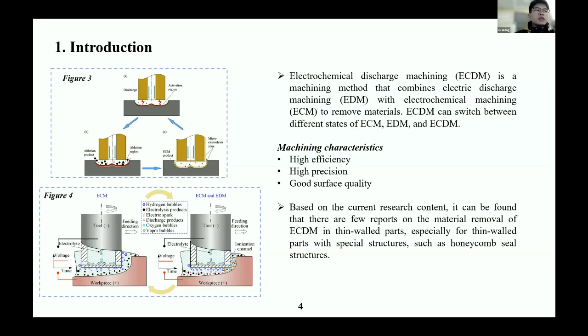In Figure 4, the initial machining stage is ECM, and there are many bubbles in the machining gap. The bubbles are the insulating medium that induce EDM. When the machining gap is smaller than the discharge gap, ECDM officially starts working. Therefore, ECDM has the advantages of high efficiency, high processing quality, and good surface quality. However, there is currently little research on ECDM processing honeycomb cell structures, which is an important reason why this study is worth conducting.